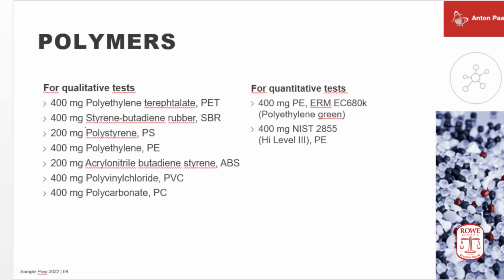So again, what we did, we mixed different kinds of polymers in one run. I'm mentioning this mixed set of samples very often because this shows the performance. In a standard classical microwave that you may know from other labs, you should not do this. You should classify your samples, you should cluster them, and you should only use samples of the same reaction behavior in one run. This is less critical with our system, and this example shows various materials from, let's say, polystyrene up to PVC for qualitative tests. What we did for quantitative tests, because we also wanted to have analytical results, is two polyethylene reference materials for analysis.